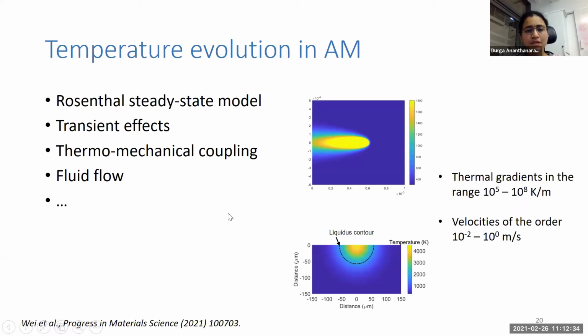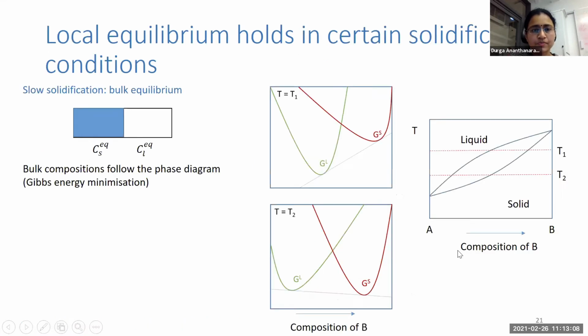So for temperature evolution, there are a lot of things we can do. But if we look at it from an approach of alloy design, the key things that we need when we want to predict the solidification later are the range of thermal gradients that we expect and the velocities that we expect. And this is typically the range that we find for SLM: 10^5 to 10^8 Kelvin per meter and 10^-2 to 1 meter per second. Of course, if needed, we can always go back and do more detailed modeling.